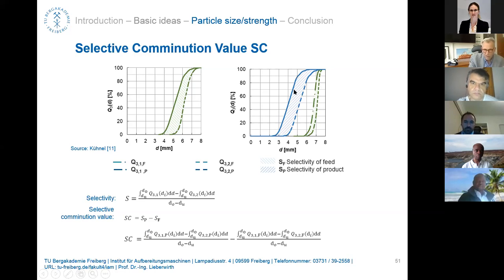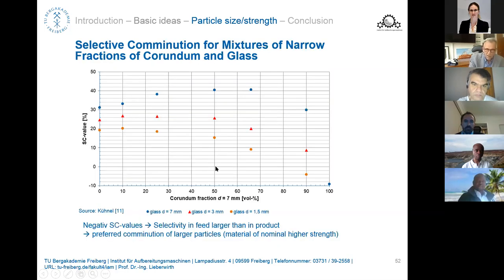So we use that space in between the curves here, between class 1 and class 2. We take the difference between the two curves, and the result could be negative or positive. It is also important to know that a negative figure would show that the particle class is finer after the comminution process. And these are the results which we have achieved with these glass beads.